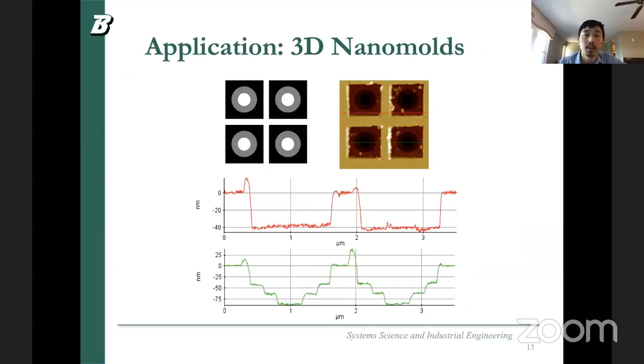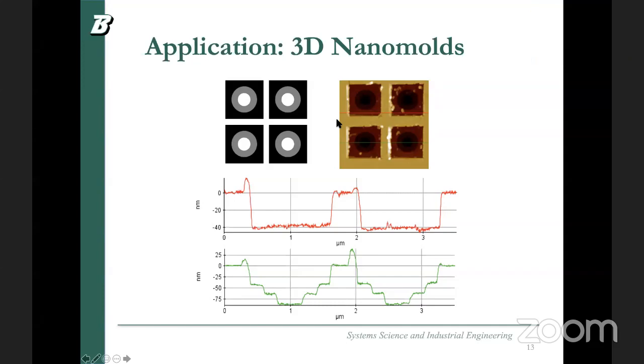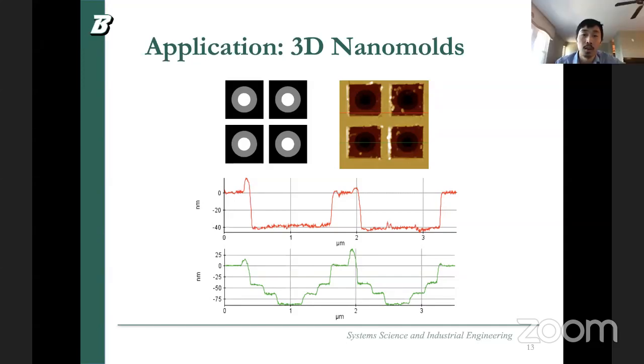So as we can see, in this application, for example, we can easily fabricate 4 identical structures using the vibration-assisted AFM-based nanomachining. So as you can see, the 4 identical 3D nanomolds. This is the design pattern. This is the AFM result directly from the image. And the picture underneath shows the cross-sectional profile of the first layer and all 3 layers. Okay, so we can see clearly 3D patterns can be fabricated with very good structure fidelity.